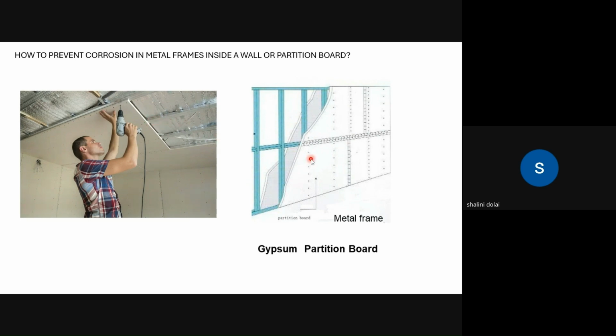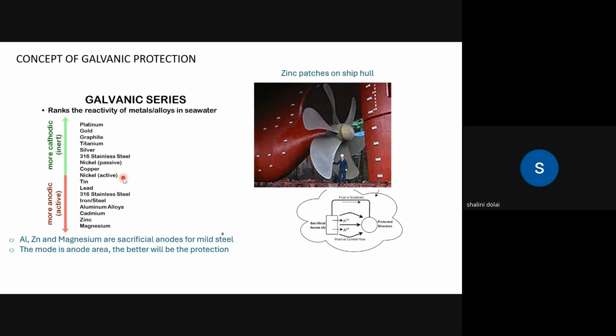And what we were using was pure zinc, 99% zinc on iron. Zinc keeps donating its electrons to my iron to protect it. While donating these electrons, the zinc gets consumed and it completely goes away from the system. Once the entire zinc is consumed, iron starts corroding and that red color bleeding happens. So using only zinc is not useful.